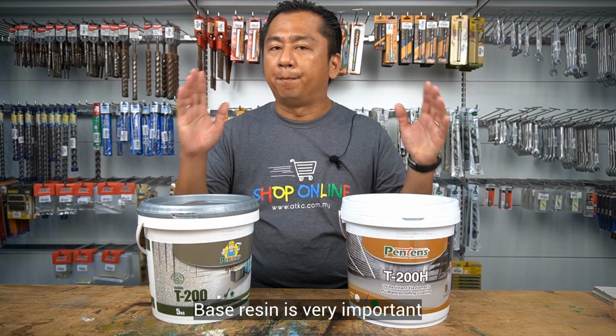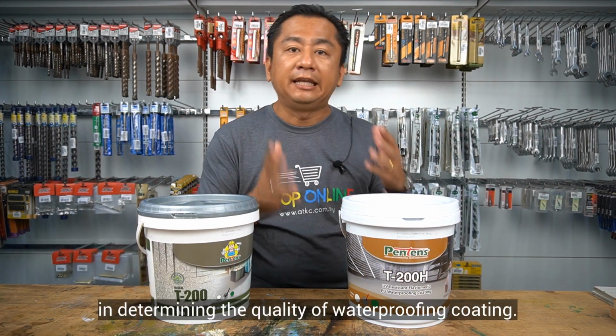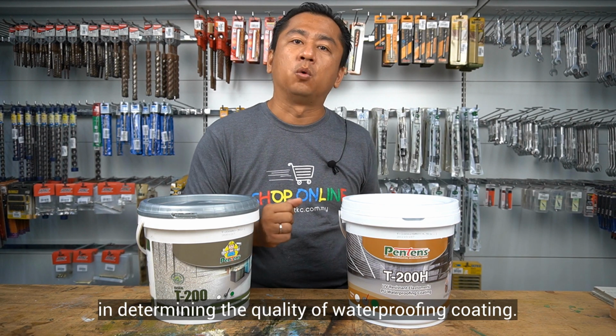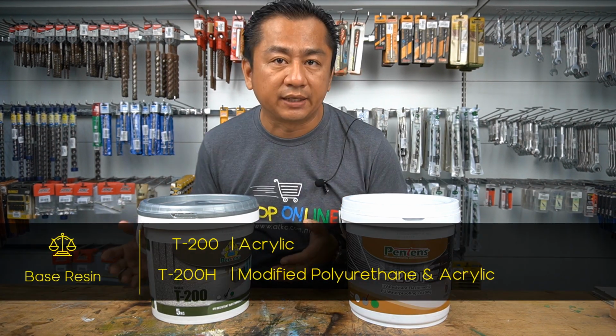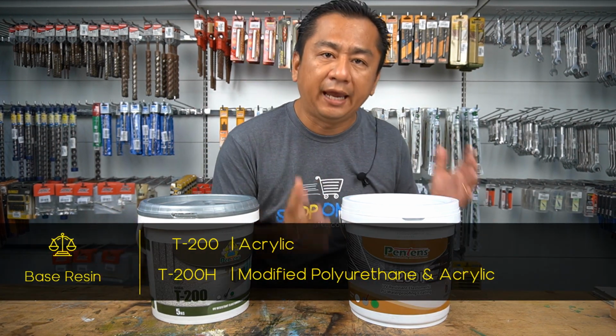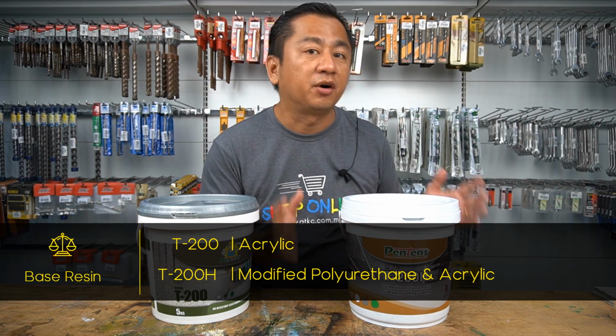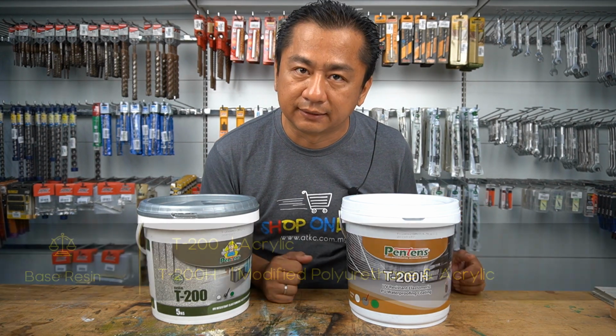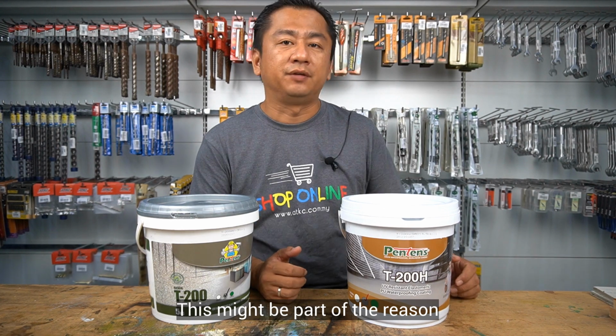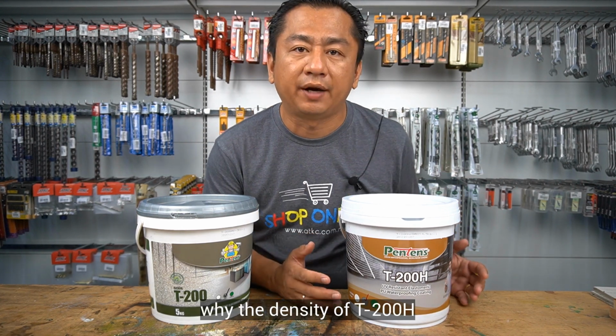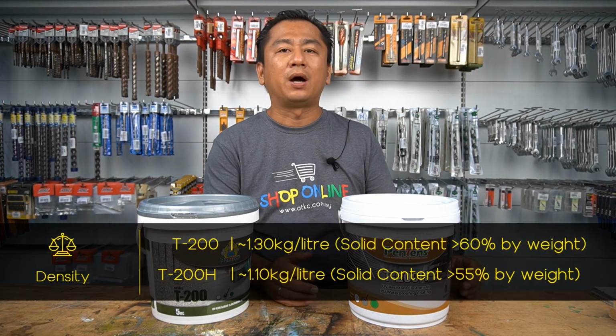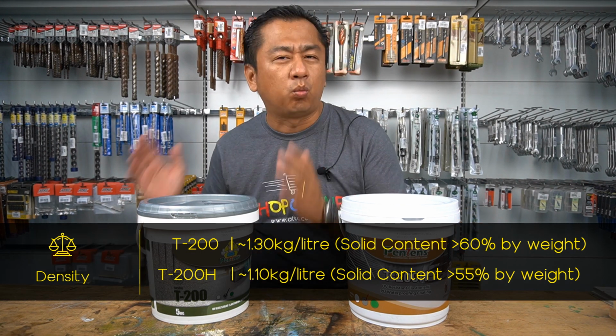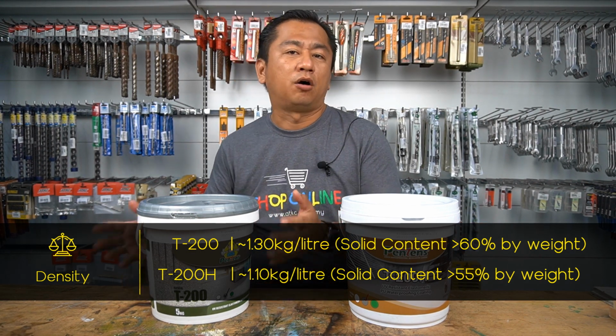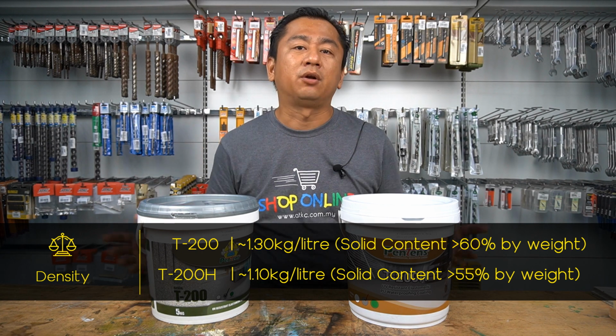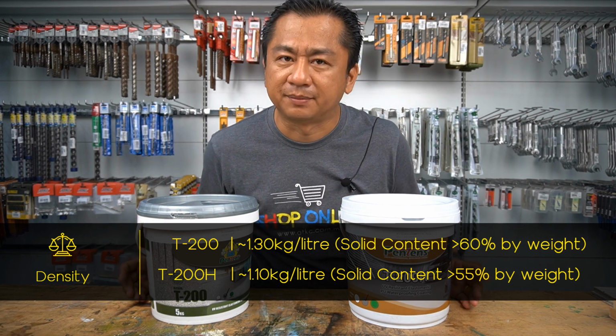T200H. Base resin is very important in determining the quality of waterproofing coating. T200 is using acrylic base, while T200H is using a mixture of modified polyurethane and acrylic. This might be part of the reason why the density of T200H is lower, 1.1 kg per liter as compared to 1.3 kg per liter of T200, while the solid content has a difference of 5%.